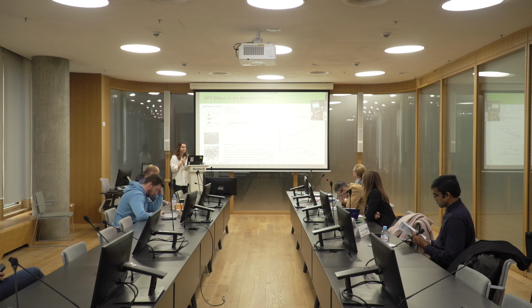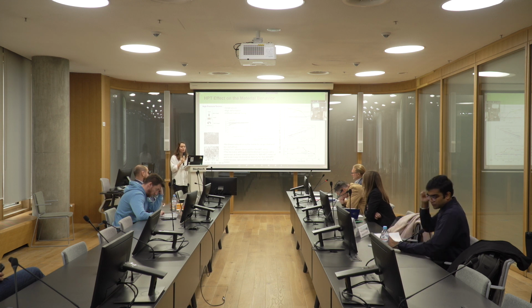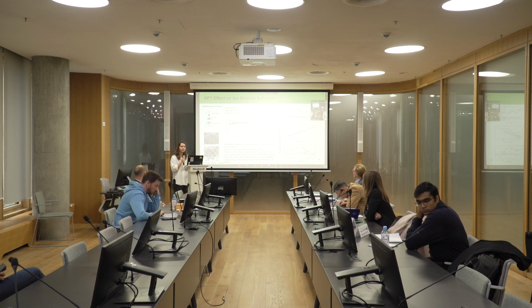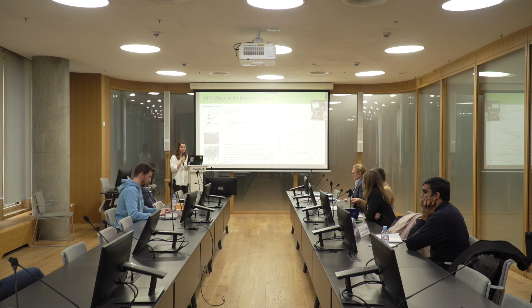As far as we investigated, this anisotropy is associated not only with texture but also with the residual stress in the material. So depending on the form of our material, the mechanical characteristics can be a little bit different. There are several ways. The first one is to apply high temperature annealing to achieve full crystallization of our material, and in this case we reach homogeneous mechanical characteristics in all directions.